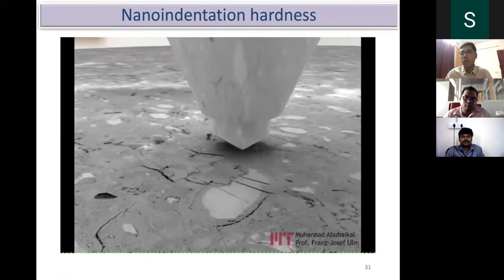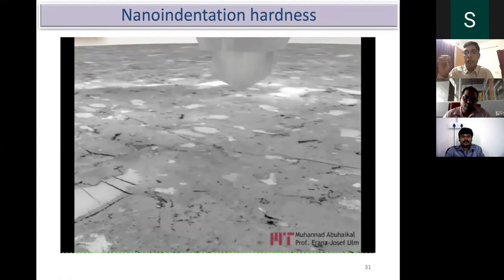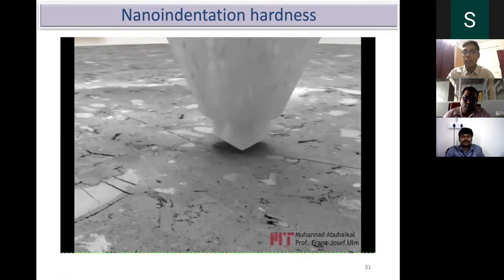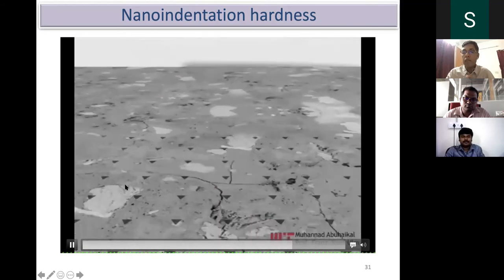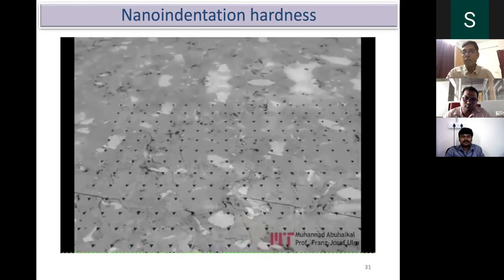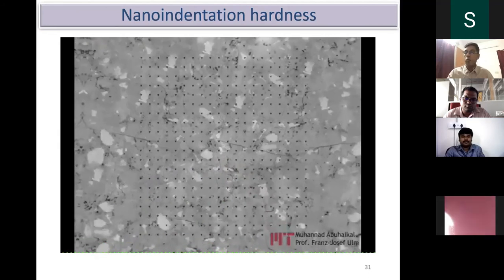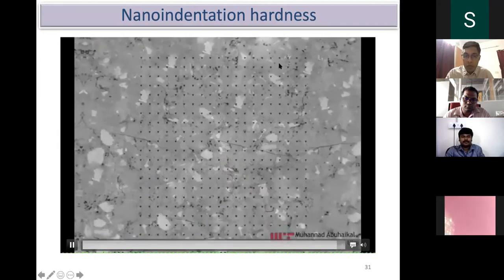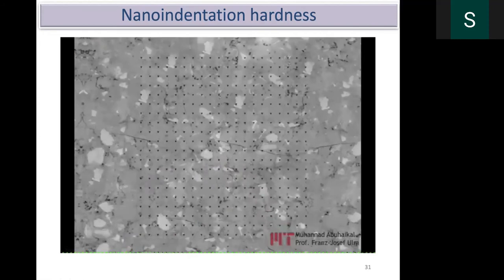You may ask a question: a conventional hardness technique creates plastic deformation, so how can you get the modulus? Interestingly, in the unloading part, the system will retrieve the elastic energy. From the initial part of the unloading curve, we can get the modulus also from the indentation. You can map the area. The indenter tip diameter is 30 nanometers, and the indents are roughly 1 micrometer apart. So many indents can be done on a 100 micrometer by 100 micrometer area, and you can completely map the hardness and modulus with this technique.